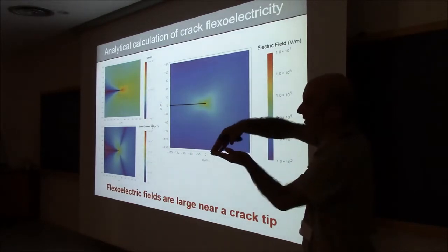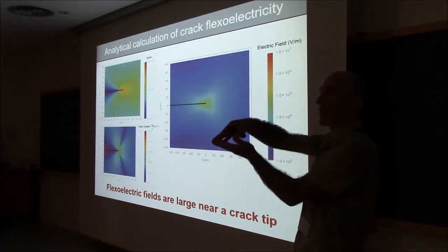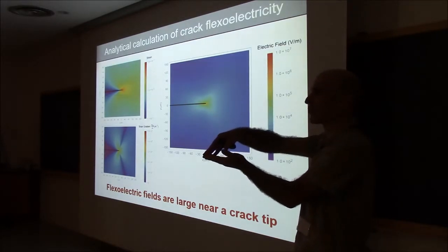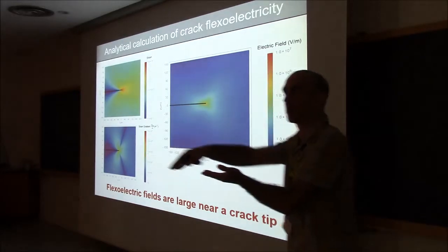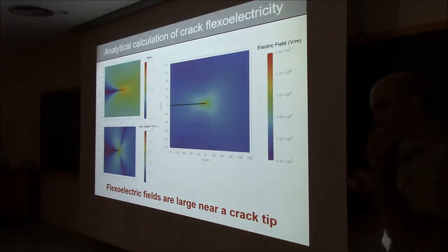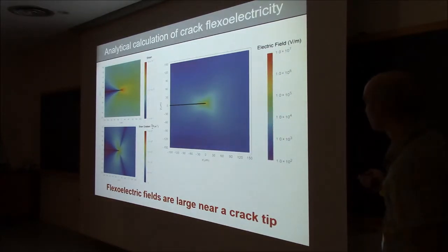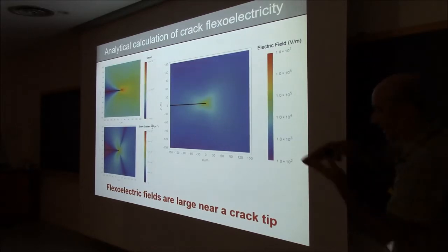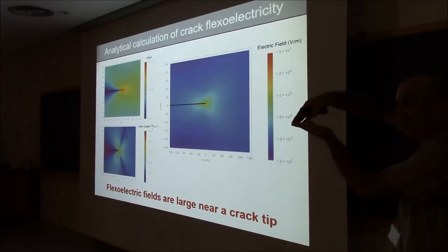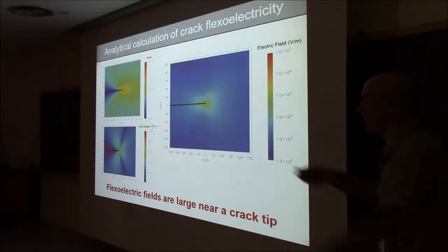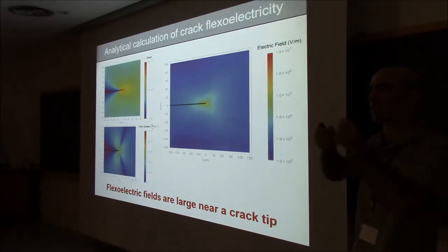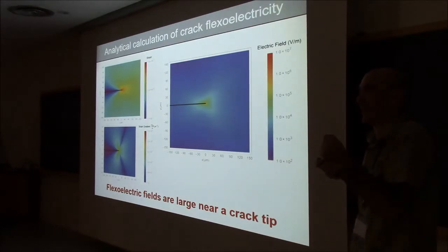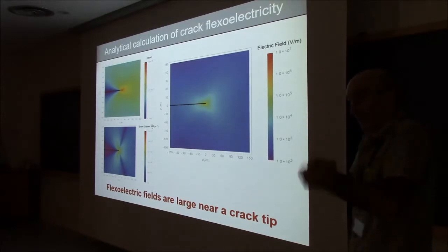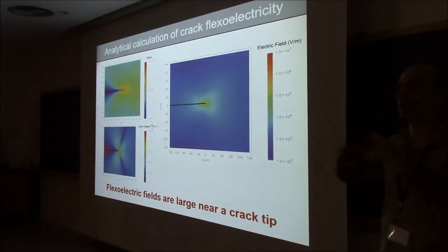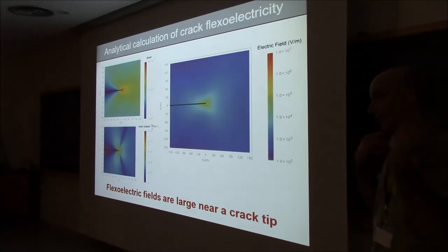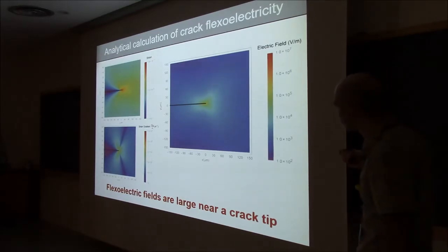the tip of the crack is under as much stress as it can withstand. If you put any more stress, the crack will advance. Okay, so here you have as much stress as your material can withstand without breaking, and the actual contact point of the two sides of the crack is atomically small. So you have as much stress as you can concentrated in as small a volume as you can. So you have the biggest possible flexoelectric polarizations and flexoelectric fields in a crack.